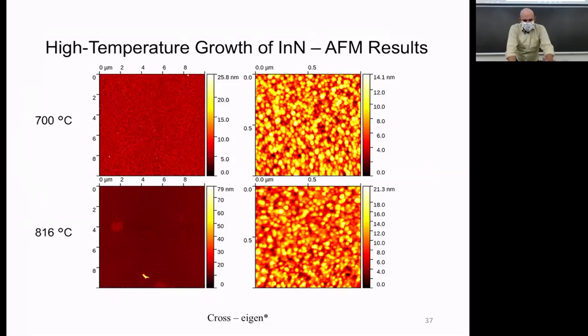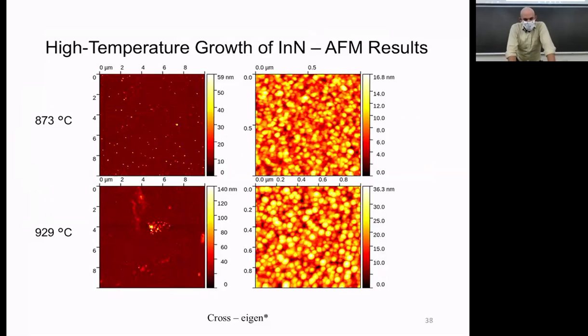And we can see the results, 700 degrees, 816 degrees. They look pretty similar, right? We get up to 873 and we start to see these little speckles on top of it. So on the left-hand side, we're seeing about a 10 micron scan, and on the right, a 1 micron scan across. And you can see that more or less the background looks the same. On the right hand, I've just taken a scan of the background, in an area where there's not a lot of those speckles.